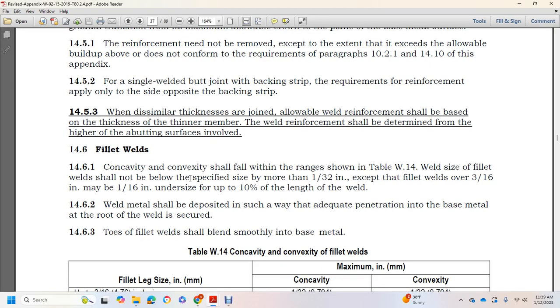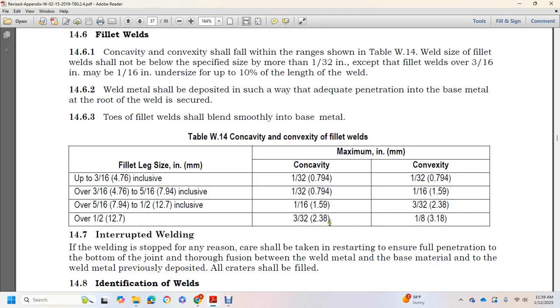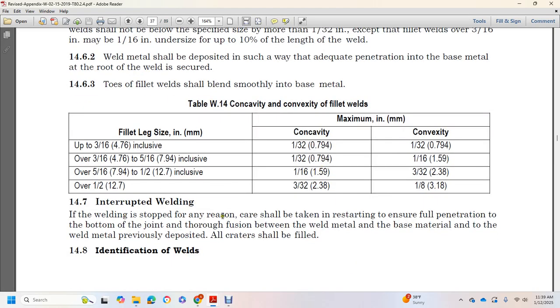Weld size. Fillet welds should not be under the specified size by more than 1/32 of an inch, except for fillet welds over 3/16 of an inch, which may be 1/16 of an inch undersize for up to 10% of the length of the weld. Weld metal should be deposited in such a way that adequate penetration of the base metal at the root of the weld is secured. The toe of the fillet weld should blend smoothly into the base metal, within the fillet weld size, maximum concavity and convexity. Interrupted welding, stopped for any reason, should be restarted with care to ensure full penetration at the bottom of the joint and thorough fusion between the weld metal and base metal and the weld metal previously deposited. All craters shall be filled.